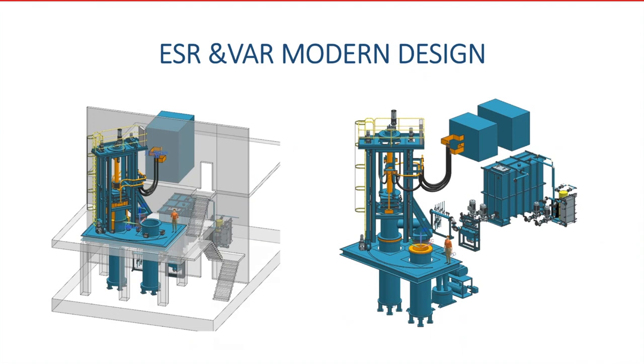To finish my talk, I would like to show you the design of modern VAR and ESR furnaces. You can see that these processes look practically like twins — the great difference is the atmosphere: vacuum versus, preferably, argon or nitrogen atmosphere during ESR. What is very important, in my opinion, is not to forget the possibility of using ESR for standard steel — not only for high-alloy steels and superalloys as is widely done today, but also for producing simple things like rails for railroads and wheels for high-speed railroads.